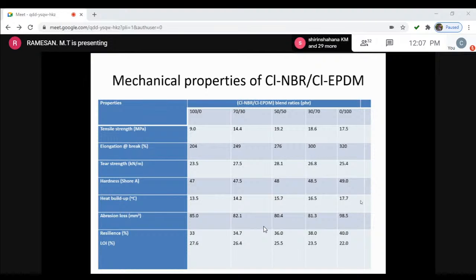A similar observation is seen for tear strength. Tear strength means how the polymer becomes torn. And the tear strength also shows the highest value at the 50-50 blend. Hardness also depends upon slight changes. Heat buildup, meaning the generation of heat in that system, is studied. Abrasion loss shows how much abrasion loss there will be if you prepare a polymer, and